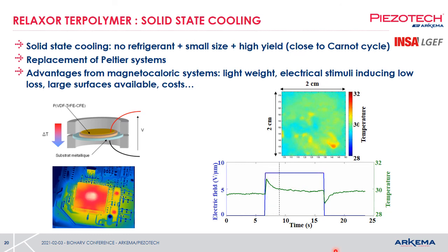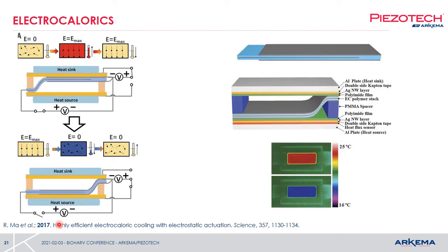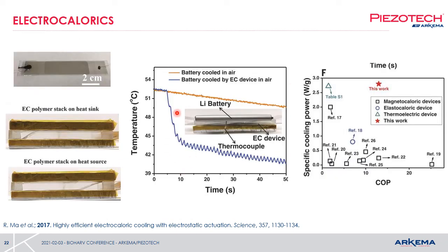Then you keep the electric field, and when you remove the electric field, you're going to increase the entropy in the polymer, because all the dipoles will be in random positions. So the temperature of the terpolymer layer will go down and then go back to room temperature because it will absorb the energy from the air. So this has been used in 2017 already by a UCLA team in order to cool a battery, and they combined the electrocaloric effect with the actuator effect. So the terpolymer layer with this kind of S shape is able to move from a heat sink to a heat source, and then after, because you have the electrocaloric effect, to transfer the heat from the heat source to the heat sink, and they have been able to cool down by more than 10 degrees a small battery in a few seconds. And this work shows very high specific cooling power, an amazing one, and there is still a lot of research on these materials.